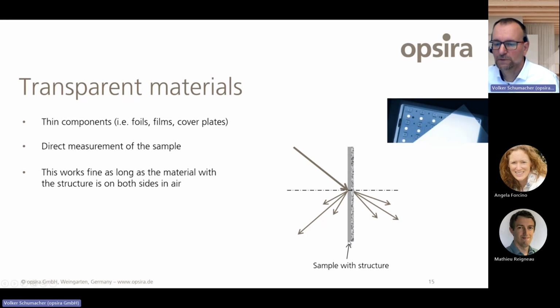We have this sample with a scatter structure on one side, and maybe on the other side it's a high polished sample. We illuminate this sample from one side and measure the scatter in transmission or in reflection. If in your application the light will be traveling not only from one side, but also from the other side, sure, there can then also be a measurement from this side, measured in reflection and also in transmission. So we have the complete information: the incidence from this side, reflection and transmission, and the incidence from the other side. And this result finally gives us such a Speos BSDF model.